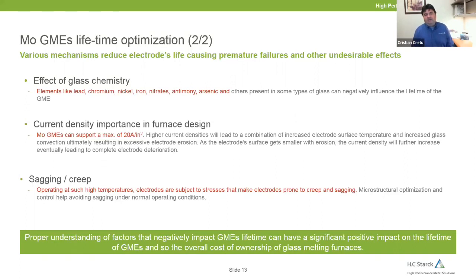And after that, if you continue at this high current, you will have a cascading effect in which you now have less electrode surface area because it's eroded, exposed to convection and higher current. So it will go down fairly fast from there. And finally, sagging and creep.